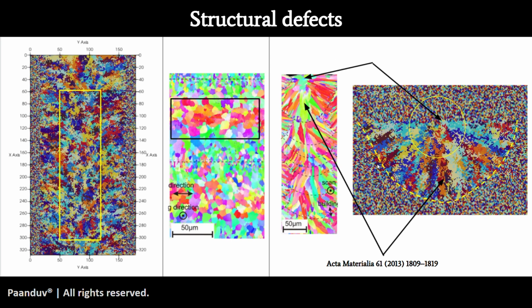And what you see in the center two images: the leftmost image is coming from AM PravaH, the second image is experiment, the third image is experiment, and the fourth image is again coming from AM PravaH. So you can see how nicely, if you look at the arrows, the equiaxed grains are matching quite well in the first two images, and equiaxed and columnar grains are matching quite well across the cross section in the last two images.